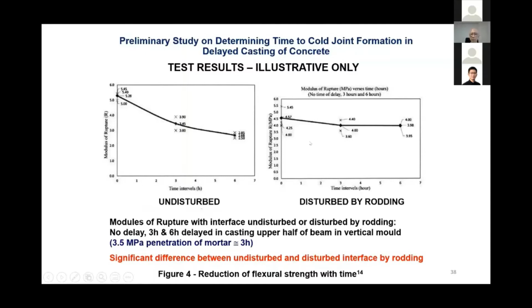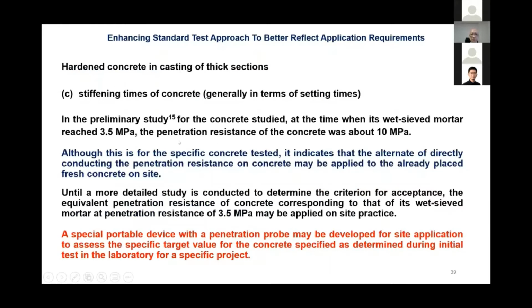So if we are a bit more detailed, we can now ask ourselves, how much decrease can a practicing engineer tolerate on a job site, knowing that the concrete is of a higher grade to start off? So that means now we have a better means of making a more rational decision. In a preliminary study, after we have done our wet sieve mortar, we decided, why can't we penetrate the concrete? There's nothing to prevent us from doing a similar test with the concrete.